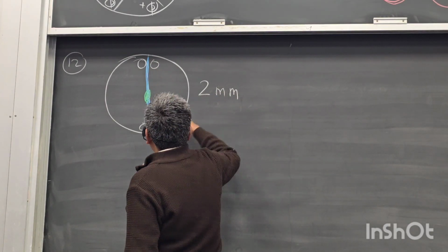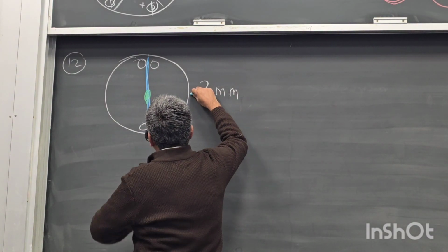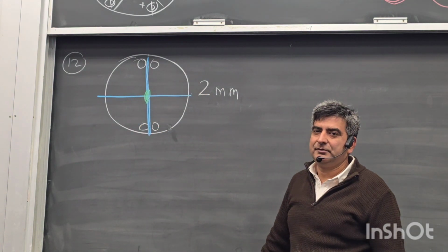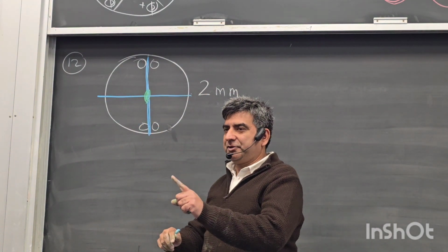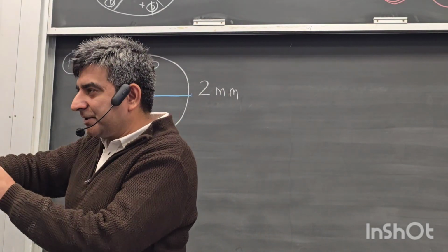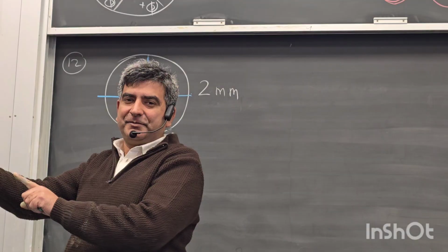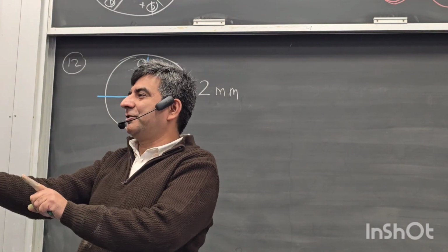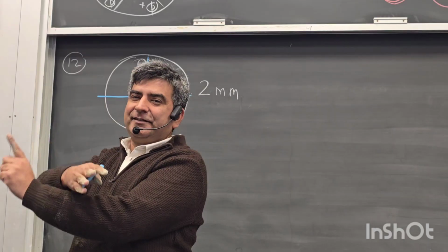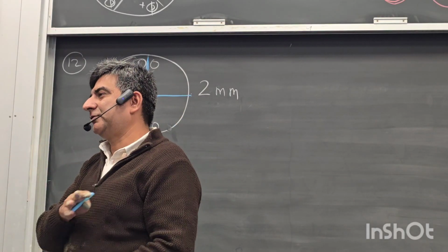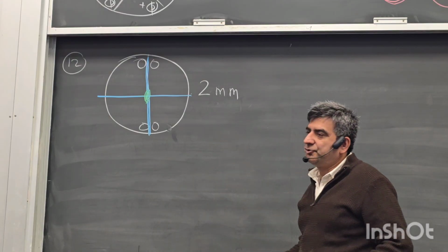There is one mirror plane, and then this mirror plane has automatically generated another mirror plane. So one symmetry operation on a particular group can generate another symmetry operation. This one mirror operation has generated a new mirror operation. So now we have two mirror planes that are mutually orthogonal to one another, and both of them are vertical. So the symbol for this point group is actually 2mm.